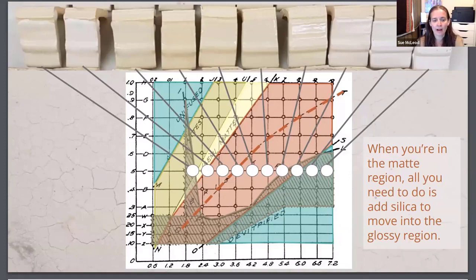Here's an example where I just did the 0.5 alumina line. I mixed a glaze for this point and dipped a test tile, and it's a matte glaze. I added some silica, dipped a test tile, and it's still matte. Then I move into satin, and then glossy, glossy, glossy, glossy. As the silica increases, eventually I have too much silica, which melts at a very high temperature for my fluxes, and then we enter the underfired region. All of these are underfired because my fluxes stay constant all over the map. If we keep the fluxes the same and just continually increase silica, our glaze won't be able to melt at our temperature. We could fire it hotter and then it'll melt, but keeping everything constant, just increasing silica, eventually your glaze will be underfired.